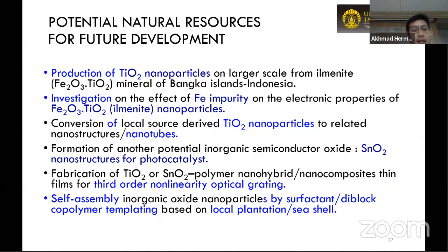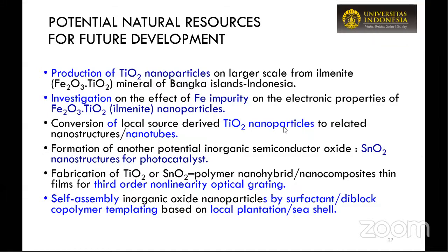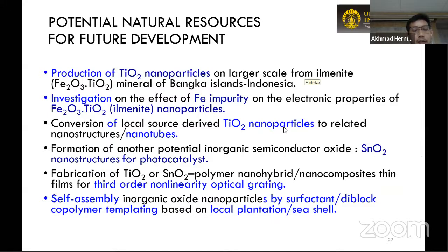When we increase the crystallinity of the TiO2, while maintaining the polymer material in good condition, we can get a very high intensity response to the laser stimulation. We can get the third order Chi3 value. We can do this also if we can find a way to embed the TiO2 from ilmenite of the Bangka Islands resources, or SnO2, the tin oxide, in this kind of nanohybrid or nanocomposite thin film, then definitely we can maybe use it for optical grating.